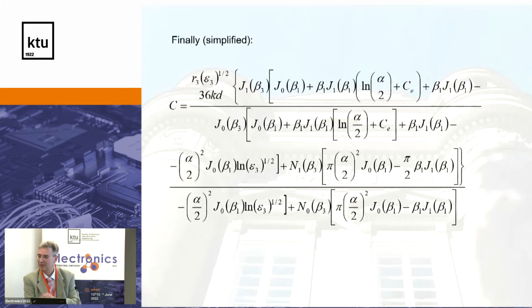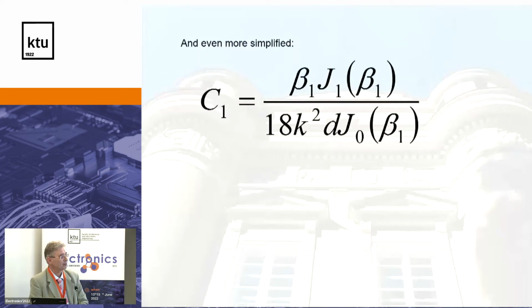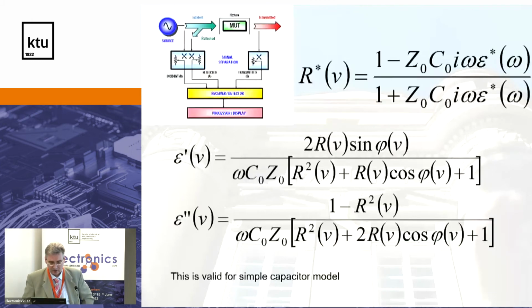Easy, I am cheating a little bit. It's not so easy. So simplifying, we have a dynamical capacitor method, which is expressed by Bessel functions. Is it working? Let's look. We have a vector network analyzer, our material under test, reflection, which is measured by the vector network analyzer. And from this, we can calculate the real and imaginary part of the dielectric permittivity. Let's have a look.